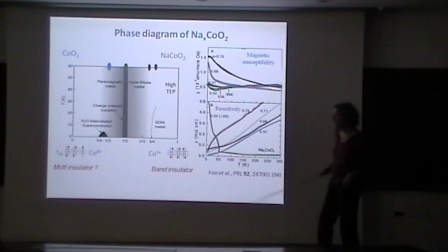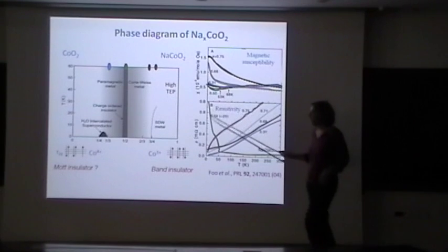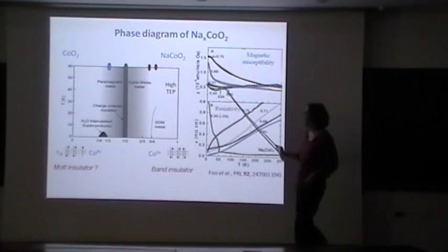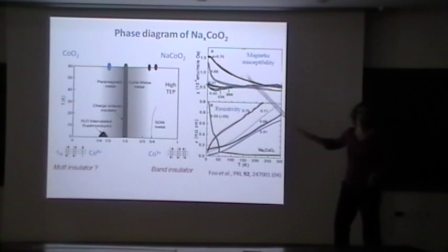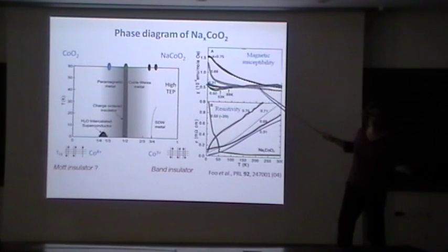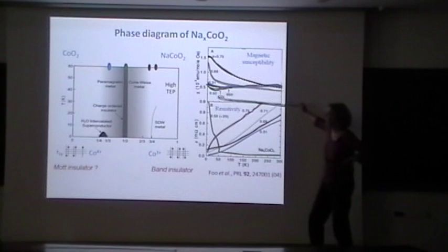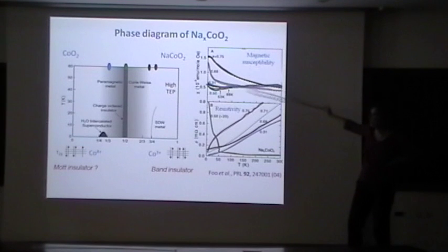But one thing that is very striking is that for these metals, if you look at the magnetic susceptibility, they seem to behave quite differently if you are in this part of the phase diagram or in this part. So in this part, if you look at this blue point here, so that's also the part where you find superconductivity, you've got an almost temperature-independent susceptibility, so that's really what you would expect for the Pauli susceptibility for a metal. And then when x is increasing, you've got more and more temperature dependence, and it looks like a Curie-Weiss susceptibility. So of course that's not what you would expect for a simple metal, but we know that if we have a correlated metal, we can have maybe stronger magnetic correlation that will give you this type of temperature dependence.